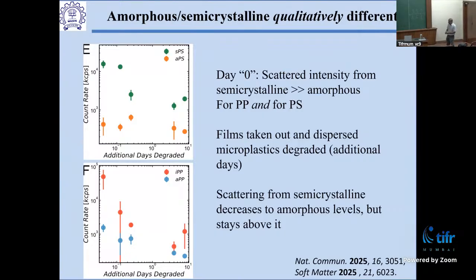So I'm taking this film, I'm putting it into this solution which has this persulfate, I etch it at this temperature, and then I take the water and I ask the question, does it scatter light, right? Because if it has particles in it, it should scatter light. And so this tells me the scattering counts, and this is data for syndiotactic polystyrene, this is for atactic polystyrene, this is for isotactic polypropylene, this is for atactic.